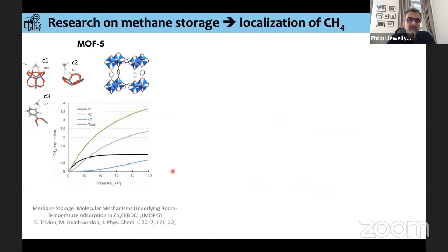Again, if we want to try and localize the methane, this has been done again for MOF-5. So what is interesting in this study is we have the total uptake here in green. And what the authors have tried to do is isolate where the methane would be with respect to the metal centers here. So this is one site here, a second site here, called C1 and C2. Then they've drawn the individual isotherms for the methane placed in this C1 and then this C2 site, and we can see that they overlap here. What the authors also show is that there's a C3 site which is close to the linker here, and this is the least preferred of the three sites. So again, the metal nodes seem to play quite an important role in methane adsorption.